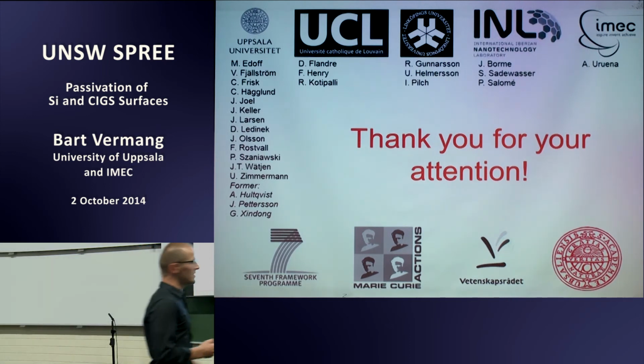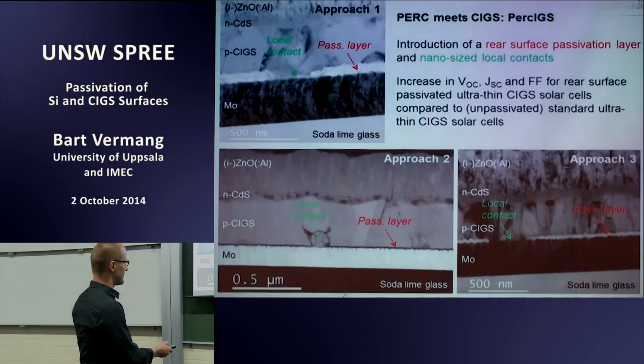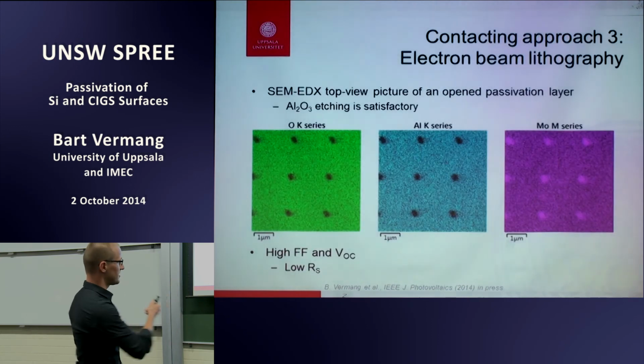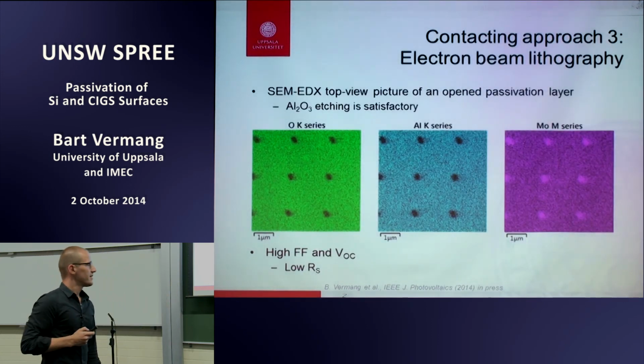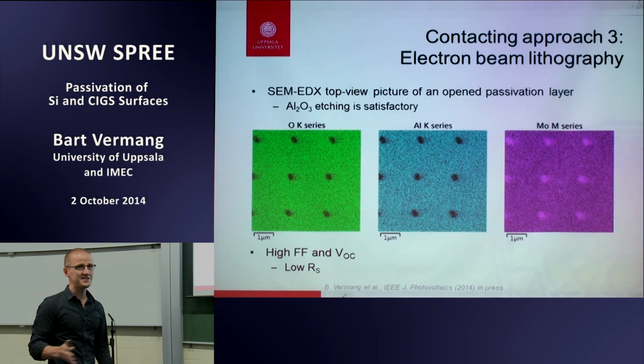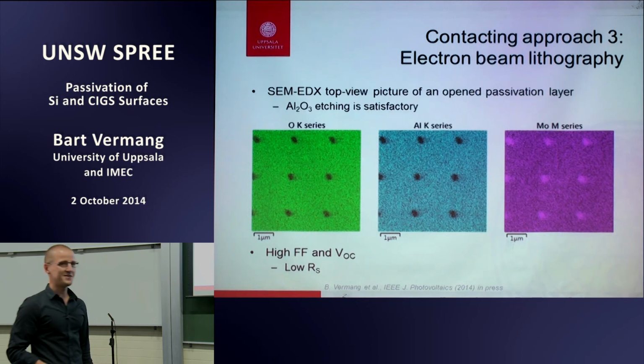Which approach achieved the highest efficiency? The last one. The E-beam lithography is something we just started. INL is helping us for the moment. They have a quite good nanotechnology lab, and they are doing the openings. We made our first cells in June or July, and those are great cells. It will be out quite soon in an IEEE Journal of Photovoltaics paper. It's a cell with a CIGS layer of only 240 nanometers, by accident. I wanted it thicker, but E-beam evaporation is not perfect. You always have some issues.